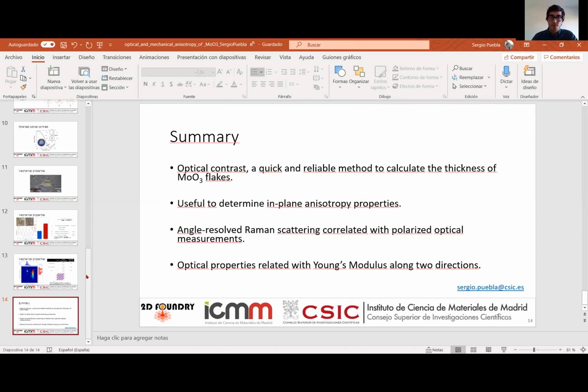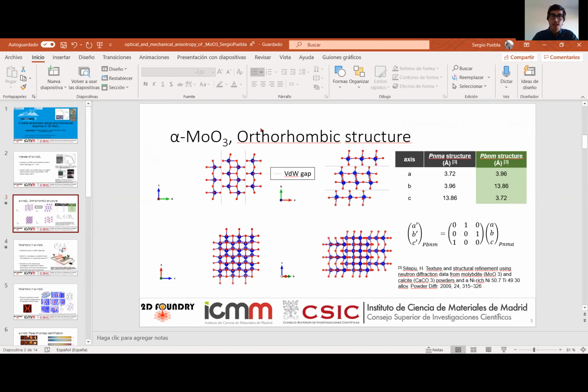Okay, and do you always get the same crystal structure for the material, or does it depend somehow on the details of the fabrication? We always reach the same structure, because this alpha phase is the most stable. This kind of material has two more phases, but once you reach 450 degrees, all the phases that you have, if you have more than one, get to this one.